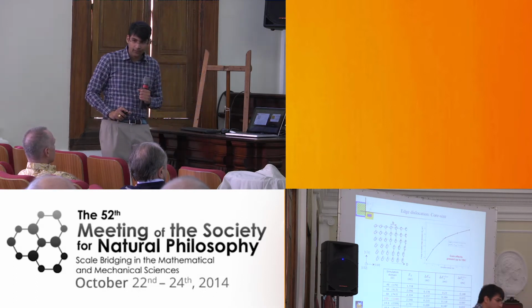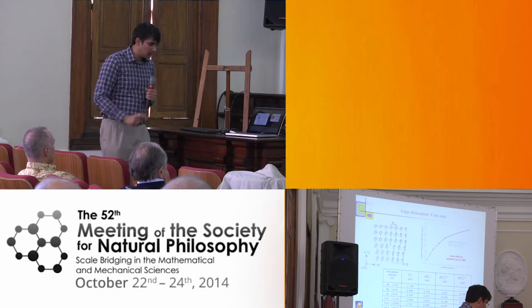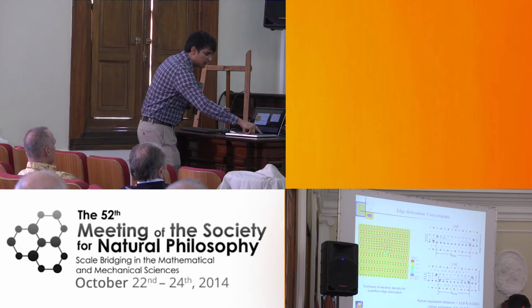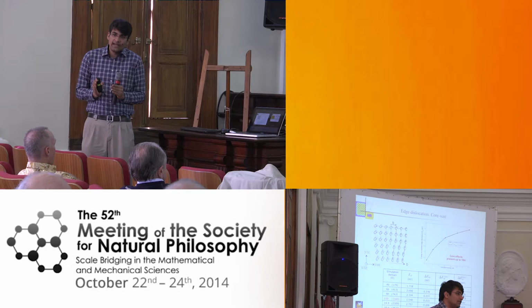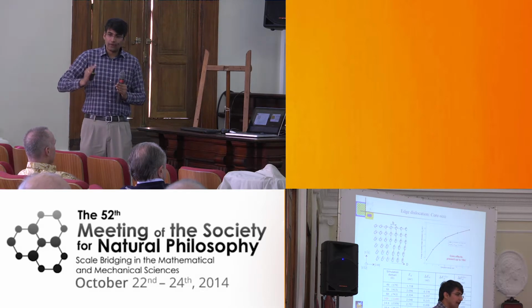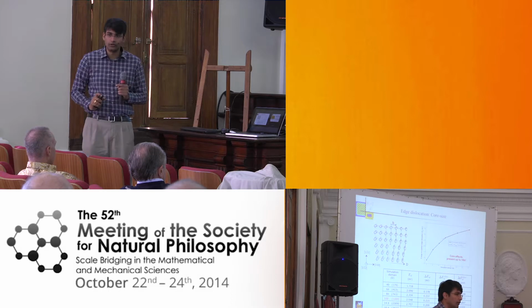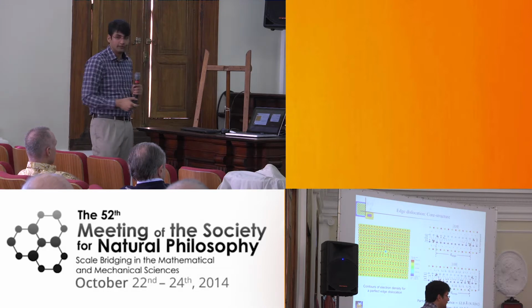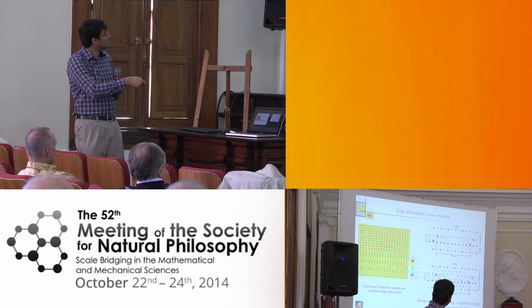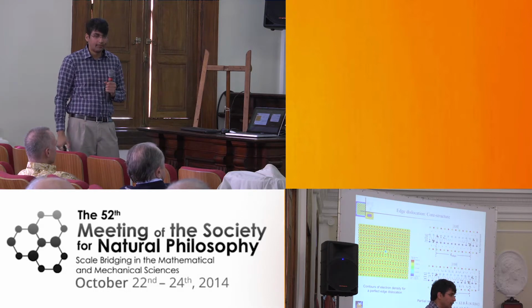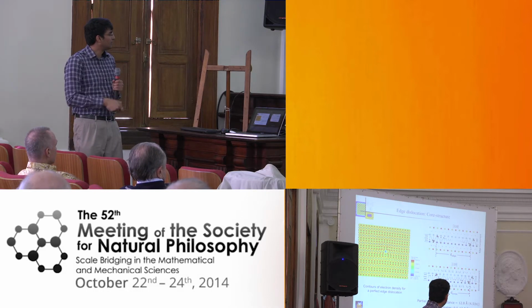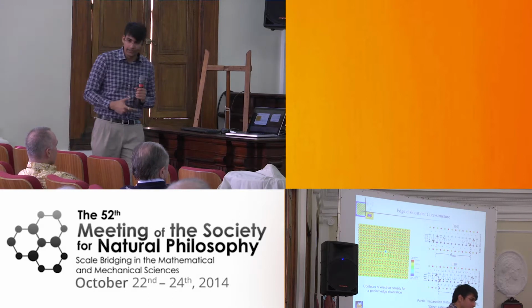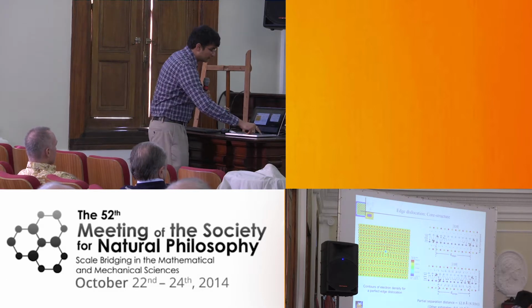So now that we have identified the dislocation core size from a quantum mechanical perspective, note that this particular calculation was done by holding the positions of the atoms fixed, because we didn't want atomic relaxations to pollute the electronic contributions. Then we relaxed the atoms, and as we all know, in FCC materials these dislocations split into partials. This is the edge component of the partial, this is the screw component, and we predicted the partial separation distance to be about 12.8 angstroms, while previous DFT calculations predicted it in the range of 10 to 14 angstroms. So we are within what previous calculations showed.